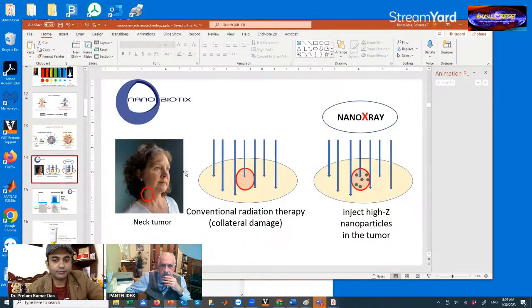The next example was Nanobiotix, a process where they put nanoparticles inside the tumor, and the nanoparticles absorb the X-rays very efficiently, and then re-emit them inside the tumor. So the tumor gets a lot more X-rays than the surroundings. So you can reduce your dosage by a factor of 9, and your nanoparticles will provide the full strength that you want, so you don't do as much damage outside. As you know, radiation of cancer doesn't just kill the cancer, it does a lot of other bad things around it. No matter how much you target it, the surrounding area is damaged.